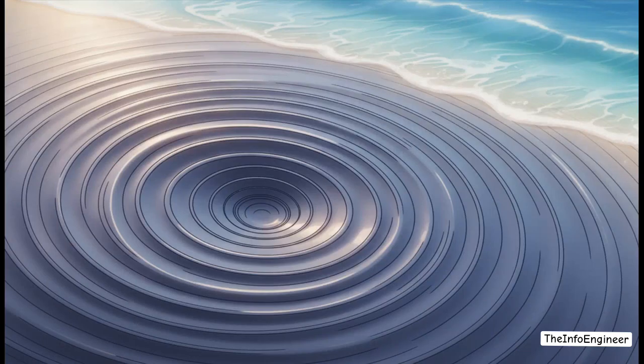And within that fatigue zone, you're going to find one of the most telling clues of all: beach marks. Just like the tide lines left on a sandy beach, these are macroscopic bands that literally trace the crack's slow advance. They are physical records of varying loads, machine start and stop cycles, and maintenance intervals that were happening over months and months before the final snap. Reading beach marks is honestly just like reading the rings of a tree.